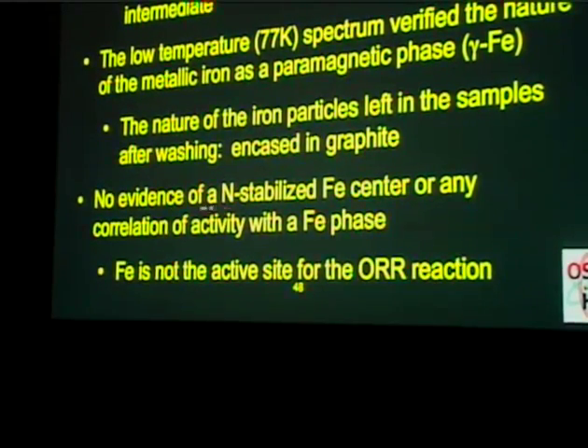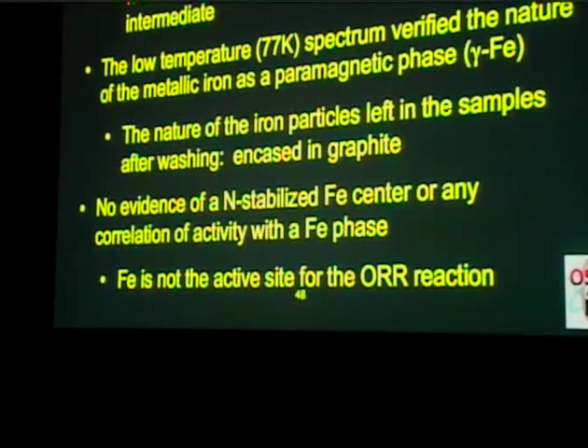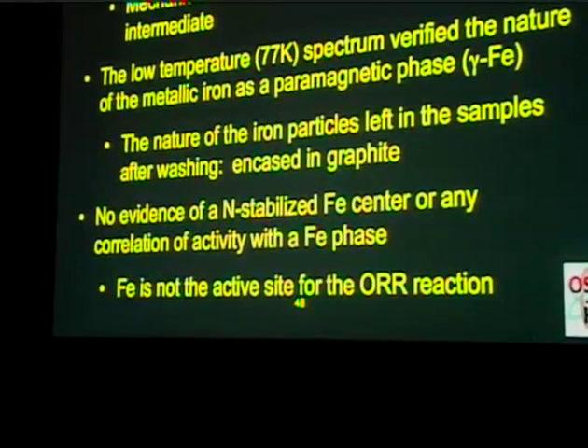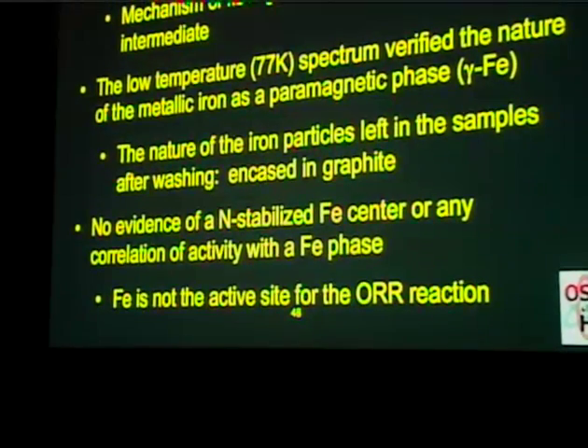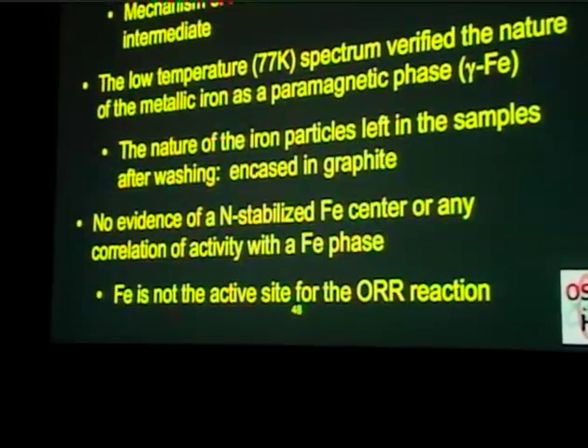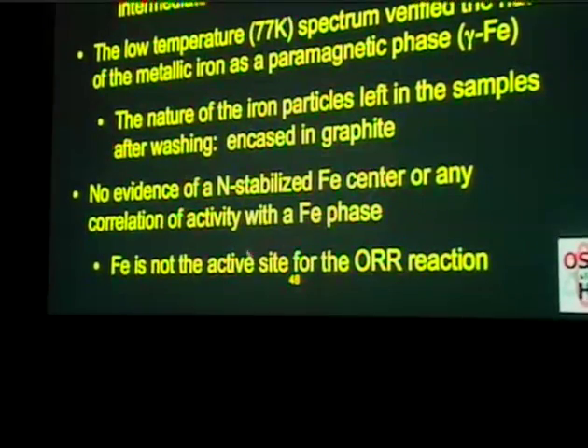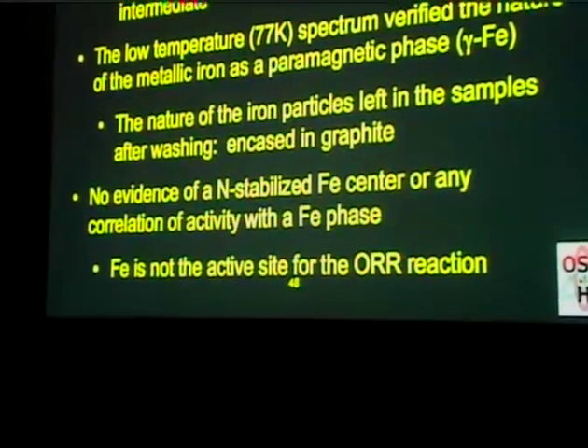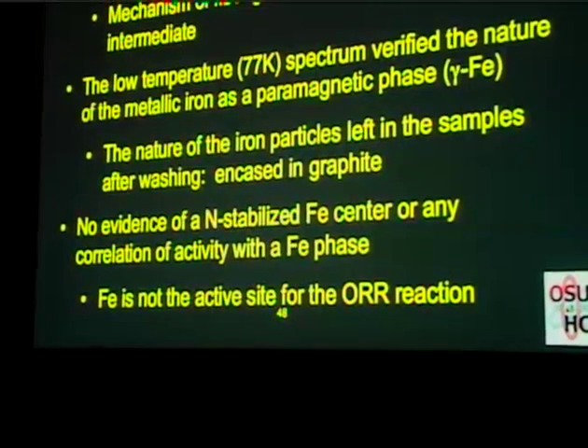And then also there was no evidence of nitrogen stabilized iron center or any correlation of activity with an existing iron phase. So this really gave us further support that iron is not the active site for the oxygen reduction reaction.